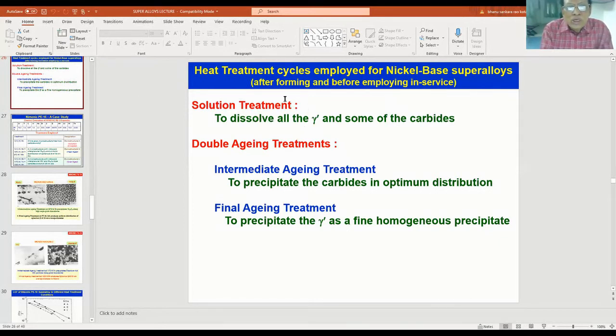So solution treatment is given at very high temperatures, about 1040 degrees centigrade and above, to dissolve all the gamma prime and some of the carbides. Because we are working at different temperatures earlier during fabrication, depending on the temperature we will be forming gamma prime and carbides, but they have to go into solution, because you have to realize the full potential of the superalloy strengthening phases by putting them at appropriate locations in the microstructure.